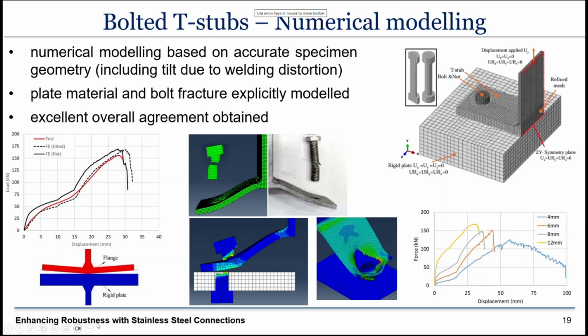For our specimens, the ones that we tested in Birmingham, we found that due to welding, there was some significant distortion in the vicinity of the welds. So we had that upwards flaring of the flanges, which, if not considered in the numerical model, significantly affects the initial stiffness. So the black line corresponds to the perfect idealized geometry of a perfectly flat flange. When we incorporated the measured distortion, which was fairly visible, that's why we measured it in the first place, we got a much better agreement between the experimental and the numerical results.